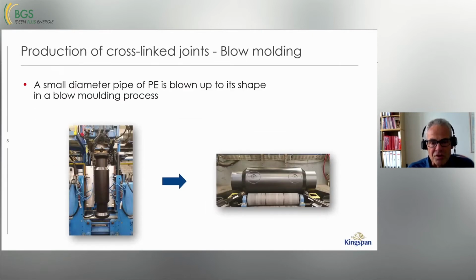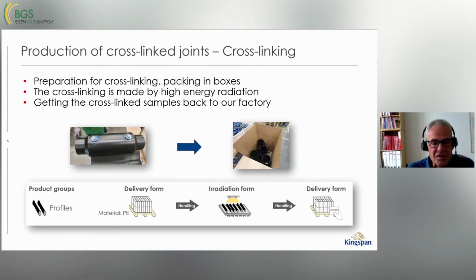Shortly about the production process. The production of a cross-linked casing joint starts with blow molding a piece of PE, like you can see on the right part of this slide. This is a piece of PE blow molded in a blow molding process, and at this point it's not cross-linked, it's pure PE. Then we prepare these samples to be cross-linked, and we pack them in boxes and send them for the cross-linking, where they will be cross-linked by high energy radiation. When the cross-linking is finished, we will get them back in the boxes, and we will be ready to produce the casing joints that we will send to our customers.